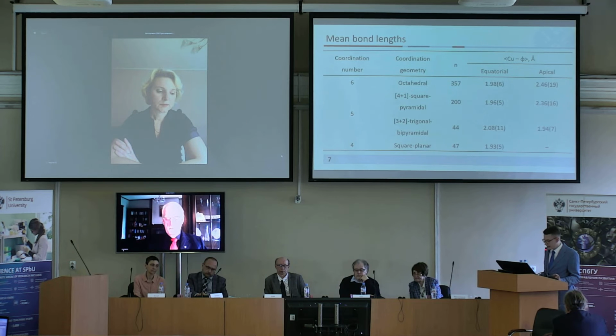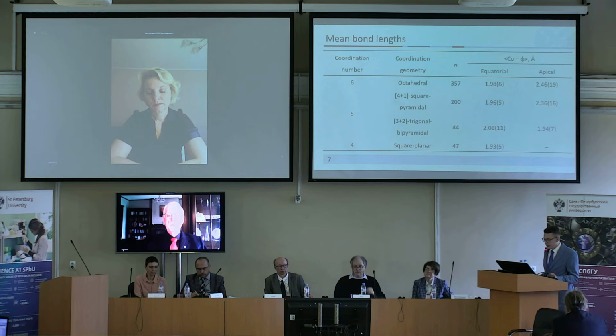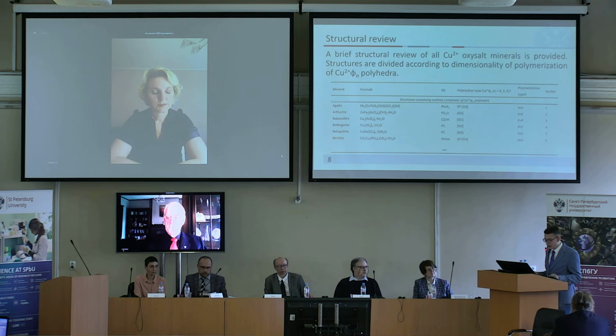The small standard deviations of the equatorial bonds indicate the relative stability of these geometries. However, the equatorial bonds of trigonal bipyramids, which show large deviations, stand out from these statistics. This is explained by the possible structural transitions between the coordination of the square pyramid and the trigonal bipyramid.